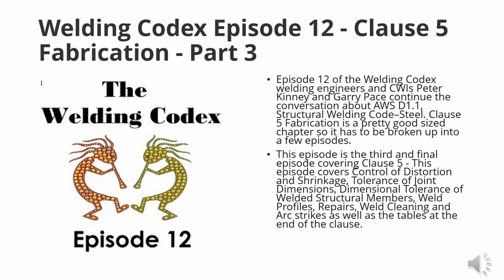Yeah, and you just have to keep track of this and make sure what materials you're working on, the industry. I worked in a foundry up in the Northwest, and we did some HY80 and HY100 material, which is more or less submarine hull material. Whenever we'd cast something out of that, there were very specific rules on how you had to weld this stuff up and remove it and grind it back flush. Basically you had to put in a temper bead to deal with the arc strike. So just be cognizant of what you're welding on, the code and the code requirements and your company requirements on arc strikes, because it's a very serious thing, especially like Pete was saying in the pipeline industry.